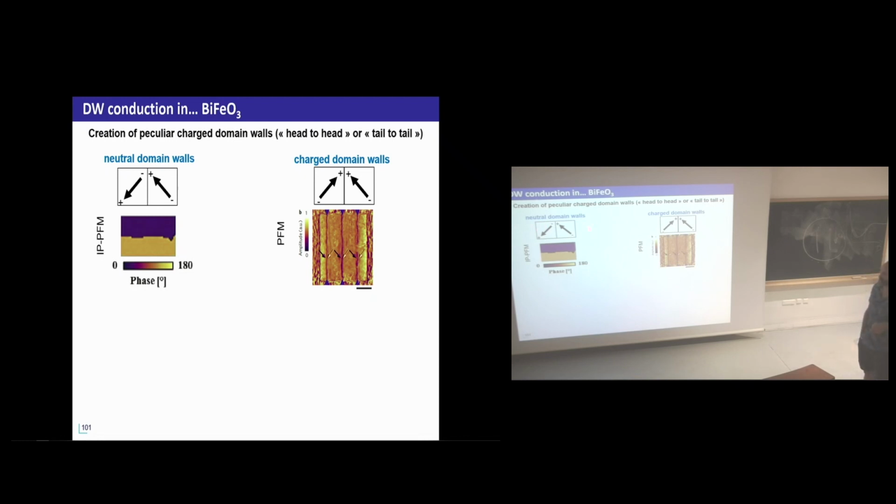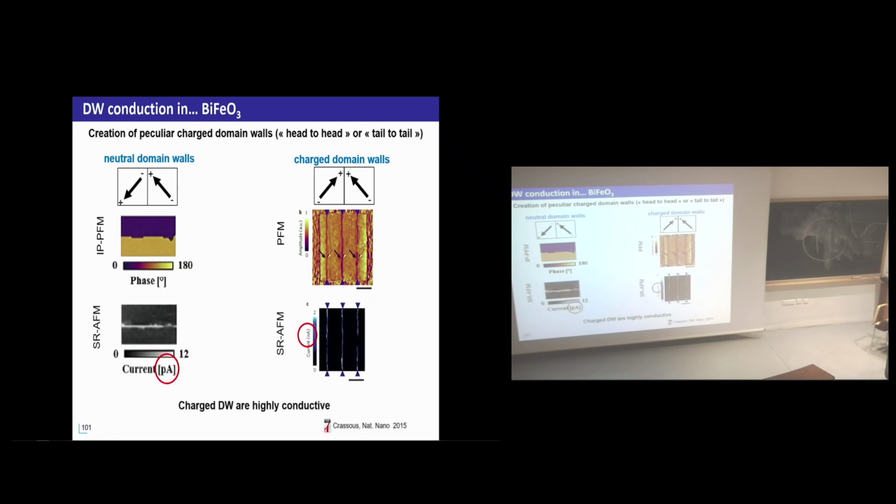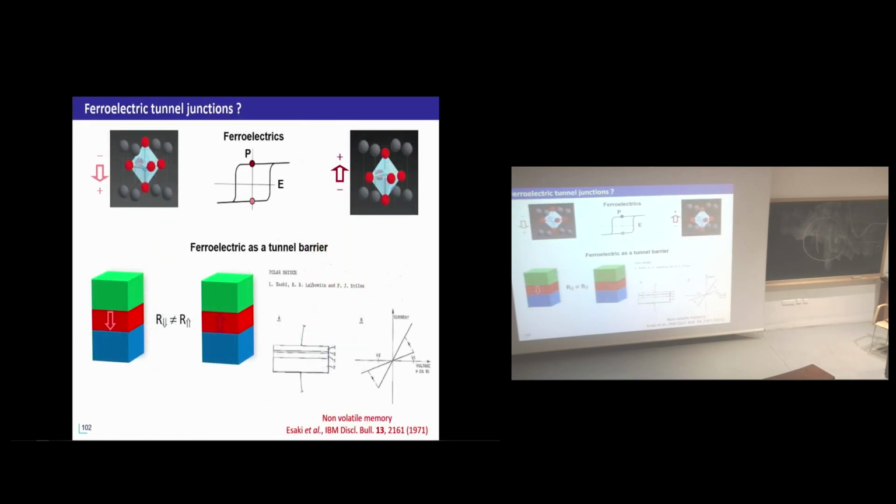So this is a neutral domain wall, which is more favorable, of course. And this is a charged domain wall that you were able to draw thanks to the trailing field. And now, if you use the scanning resistance microscope, you can see that there are at least 2 or 3 orders of magnitude difference in the conduction of the neutral domain wall compared to the charged domain wall. So, if you're interested in conduction in domain walls, scanning resistance microscopy is for you. And PFM. Okay, there is an even much cleverer way to...